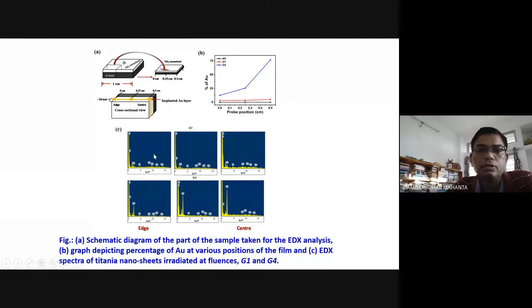In the EDX also you could see, in the first sample you do not have gold, very little. And then now this gold peak has improved up to this. So slowly it is increasing with radiation doses. On the top surface you will not get it. You get it after 26 nanometer or so, which was actually the projectile range at which you get maximum number of gold atoms.